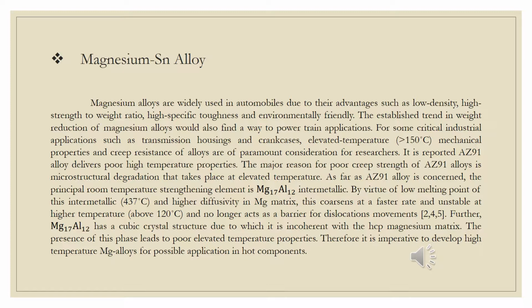It is reported that AZ91 alloy delivers poor high-temperature properties. The major reason for the poor creep strength of AZ91 alloys is microstructural degradation that takes place at elevated temperature. As far as AZ91 alloy is concerned, the principal room temperature strengthening element is the Mg17Al12 intermetallic. By virtue of the low melting point of this intermetallic, which is 437 degrees Celsius, and higher diffusivity in the magnesium matrix, it coarsens at a faster rate and is unstable at temperatures above 120 degrees Celsius, and no longer acts as a barrier for dislocation movement.